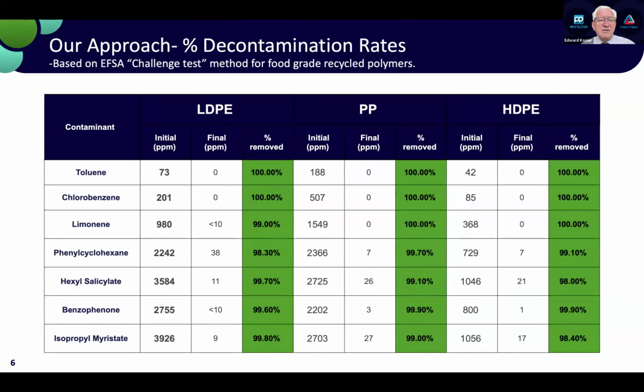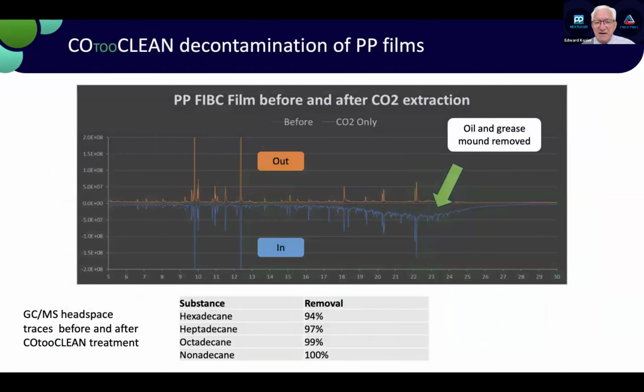But when we apply the recycling process, we can remove typically 99% or going up to 100% of these materials. In other words, beyond the limit of detection. And that's uniform for PP, HD, and low density. And this is another trace which shows the capacity to remove oil and greases. This is a sample of PP film material.